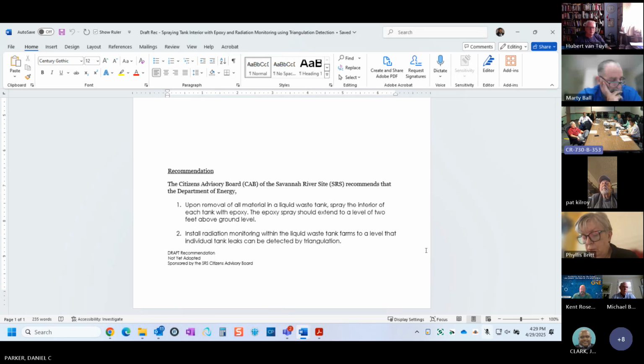If there is, well, the PA modeling uses the mechanism of diffusion, where soluble contaminants move through a film of pore water. Another mechanism would be infiltrating water from the surface, somehow gets into the capped closed tank and travels 35 feet through the concrete and out the bottom. Well, that's a slow process, if it happens at all, and it depends on the integrity of the cap and the watershed capabilities. So for this case, I don't think a coating of epoxy or any kind of polymeric material would help, and it may make things worse. Because the coating interrupts the passivation that's obtained from the high pH and chemically reducing conditions that keep the metal intact. Does that help at all?